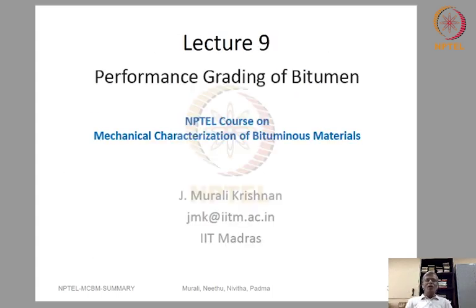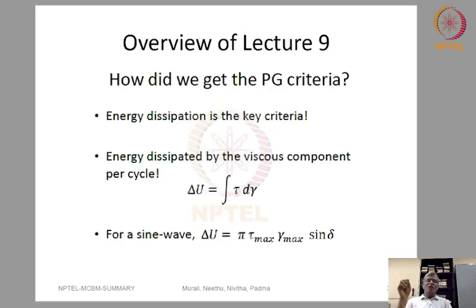Then this lecture continued in 9, because I wanted to show you how from the fundamentals we got this PG criteria. Because you use G star sin delta, G star by sin delta, you really need to understand where this is coming from. So what it means is, energy dissipation is the key criteria. In fact, we want to find out what is the energy that is dissipated by the viscous component per cycle. How do you really define energy dissipation? If you take a material and do a lot of work on the material, when you unload it, how much of the energy are you able to get back, and how much is completely dissipated? That is what it really means.